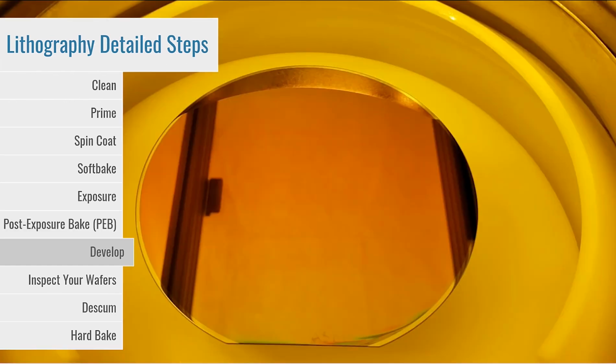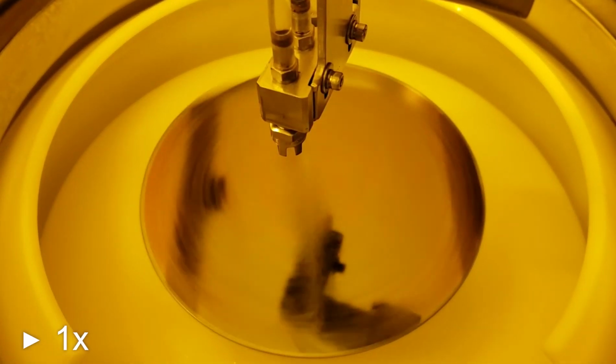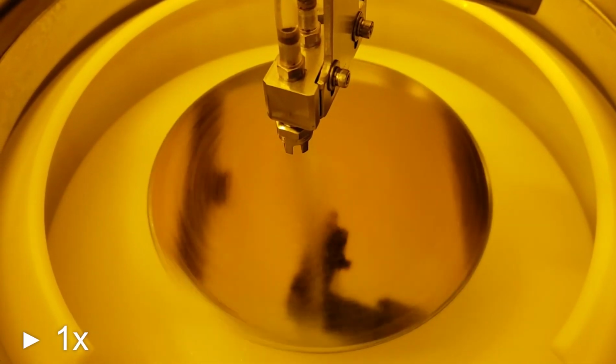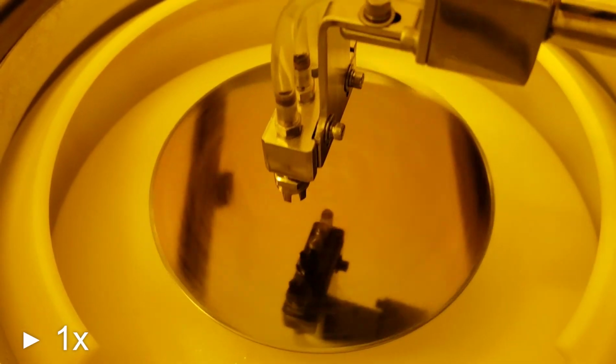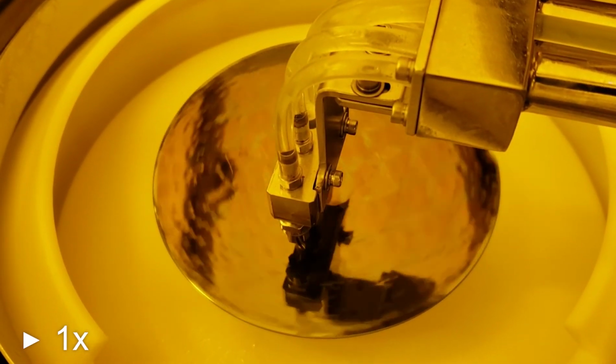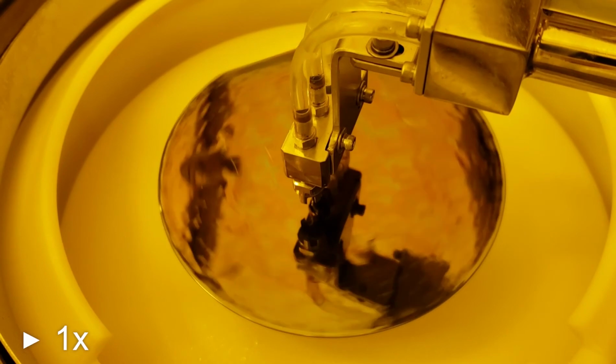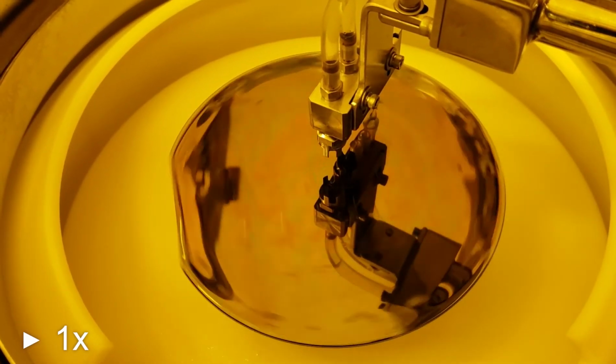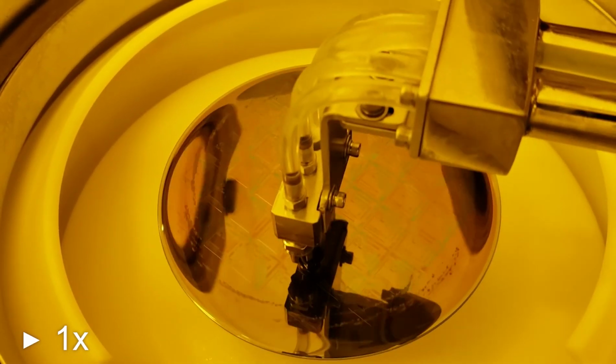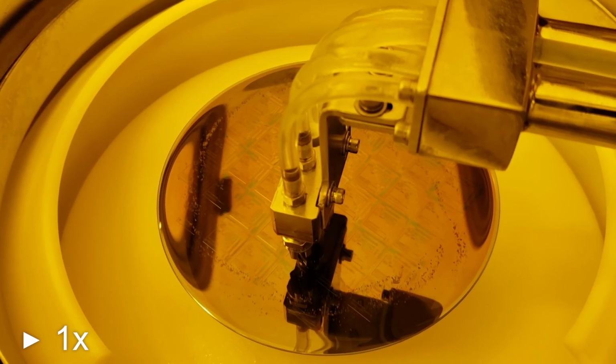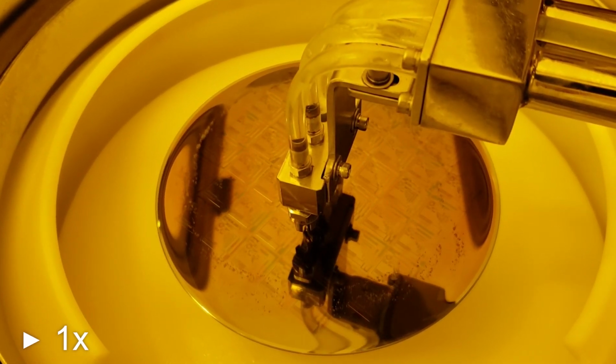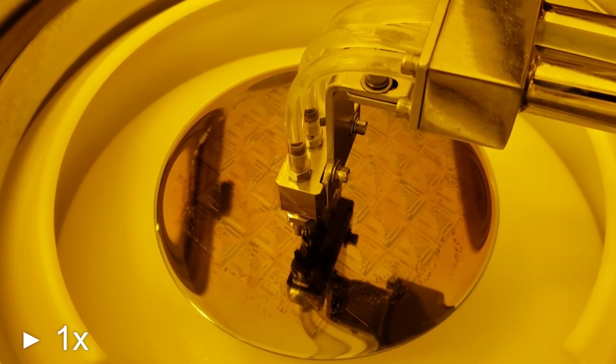On a track system, the develop, rinse, and dry steps are automated. First, the nozzle sprays the wafer with chemical developer. This is done to wet the sample surface, and without it, the developer would flow off the wafer. Next, a stream of developer is dispensed to form a puddle on the wafer. The sample sits in this developer puddle for a set amount of time.